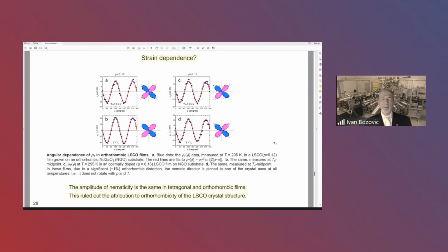Lanthanum strontium aluminate is purely tetragonal, while neodymium gallate is orthorhombic, with about 1% difference between a and b. So it's a large orthorhombic distortion by crystallographic standards. But as you can see, the lattice distortion is larger by 1 or 2 orders of magnitude, but the amplitude of nematicity is almost the same in films grown on lanthanum strontium aluminate, which is perfectly tetragonal, and in these lanthanum strontium cuprate films, which are very, very orthorhombic. The only difference is in the orientation. And this also points to a purely electronic origin.